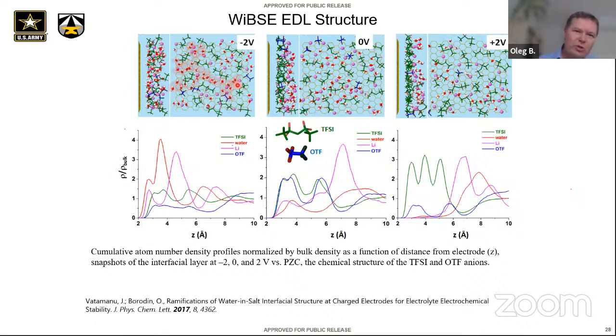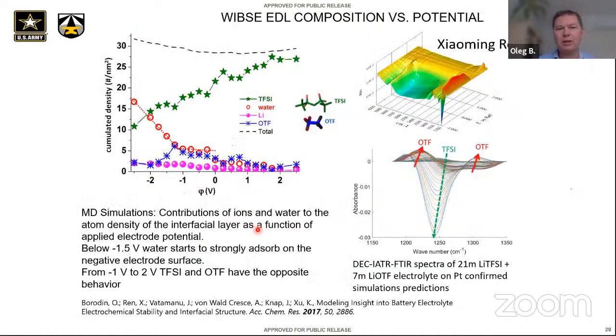Lithium with water comes in, and unfortunately it brings water. So eventually, if the SEI is not very robust and there are cracks developing, lithium will start bringing water, and that's a challenge. It highlights challenges at very, very large negative potential for the water-in-salt electrode.